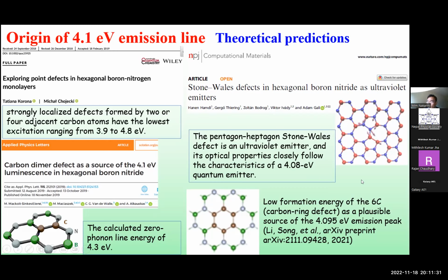For example, it's a hexagon, but in some places it is 5, in some places it is 7, and still the average is 6. So that could be the origin, and that's called a Stone-Wales defect. And another report is that if 6 carbons are sitting in a ring, as a hexagon, that also gives an energy close to 4.095 eV. So these are all theoretical calculations, but one similarity in all of them is that it is definitely a carbon-related defect, and to find what exactly the defect is, we need further experimental evidence.